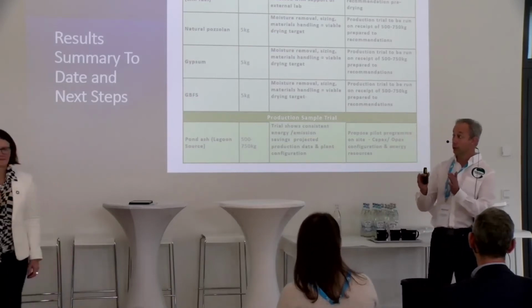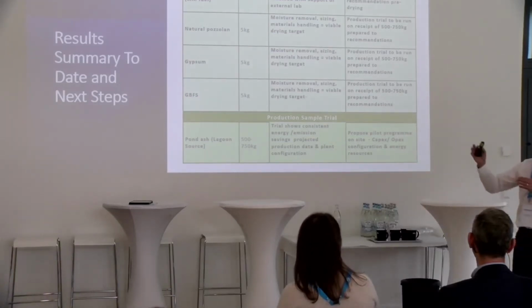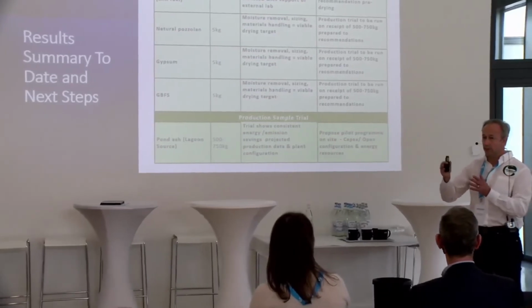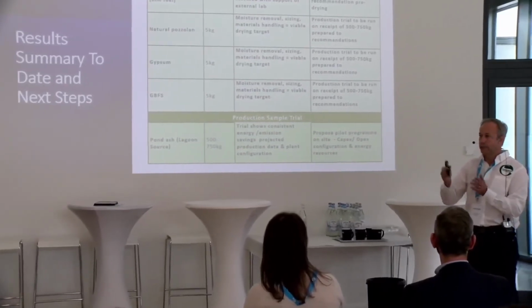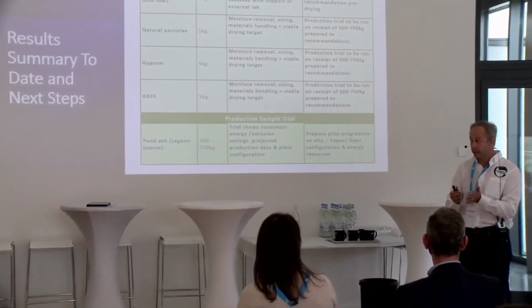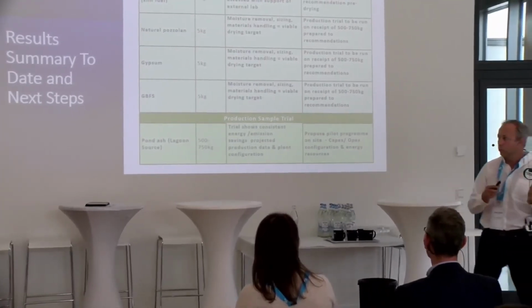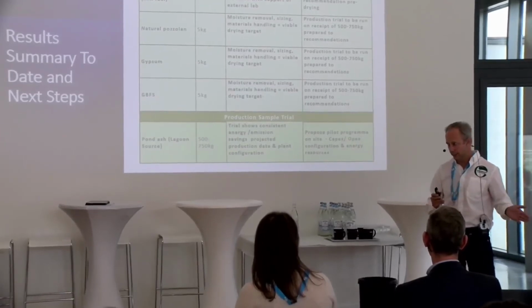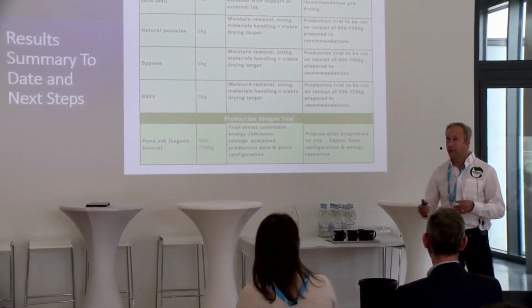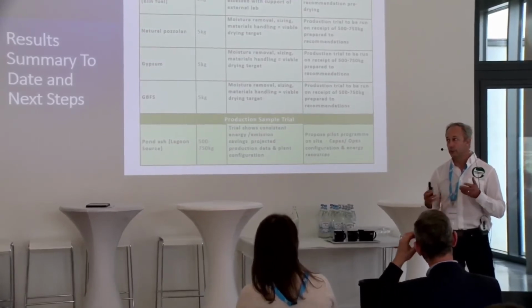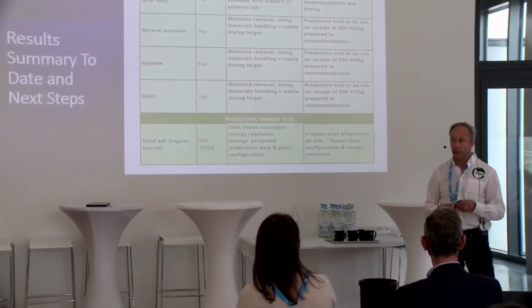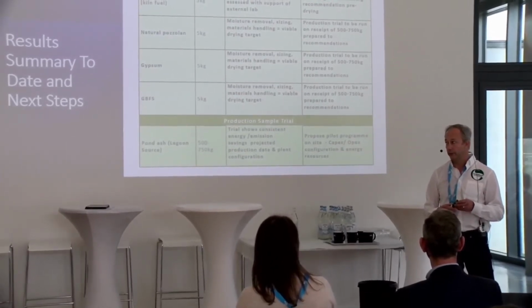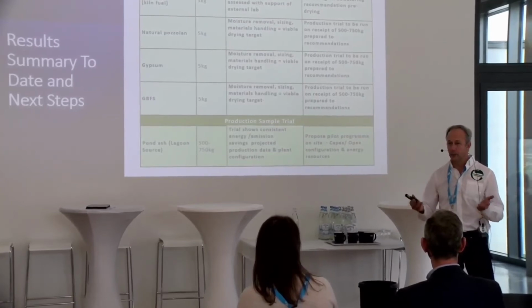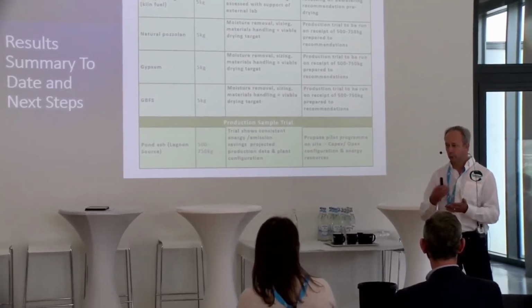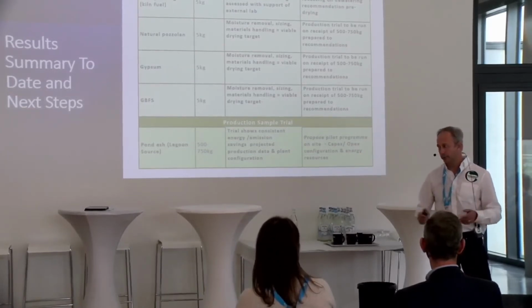Ash is about on the border between those two requirements. So usually we would say to people, dewater down from, you may be starting at 30% or more, down to about 20, if you can, into the mid-teens, and then dry. So our machinery works best with fly ash, from the mid-teens down. In terms of the cost, for a typical 4 to 6 ton per hour unit, that would be about 700,000 US dollars. I want to caveat that answer because it's very much a shot from the hip. It all depends on your particular situation, how you are going to configure the plant, the trade-offs that you choose to make, but it's of that order.